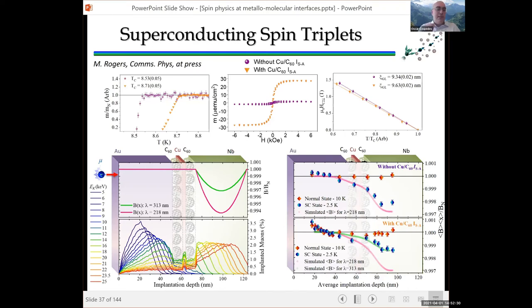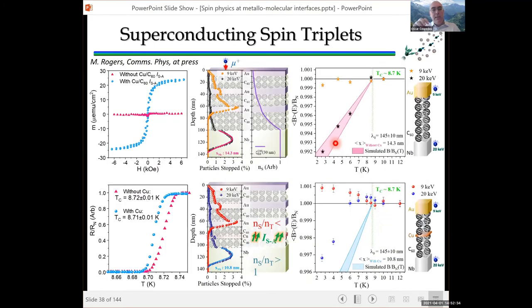copper C60 interface. So that means our Cooper pairs are diffusing into the C60, so we can detect the diamagnetic signal in the C60. And then they are converting into paramagnetic Cooper pairs that then propagate all the way to a gold layer that is some 50 nanometers, well, between 25 and 50 nanometers above the niobium. So the copper C60 interface is converting the singlet Cooper pairs into triplet Cooper pairs.